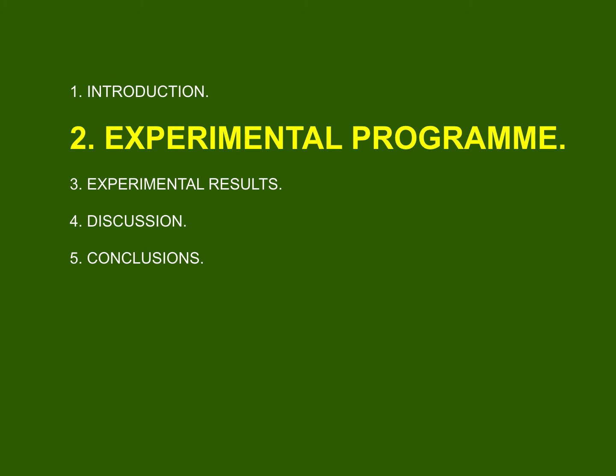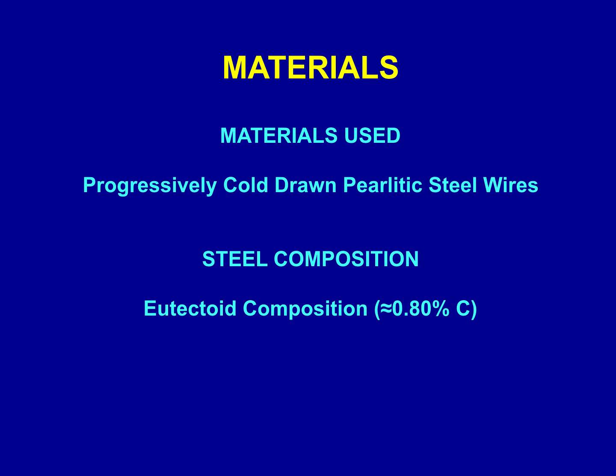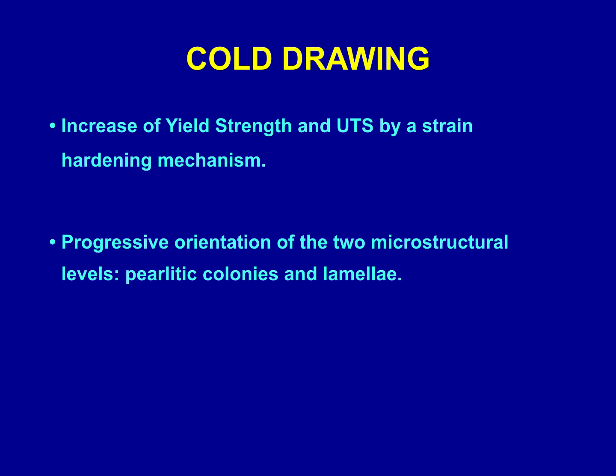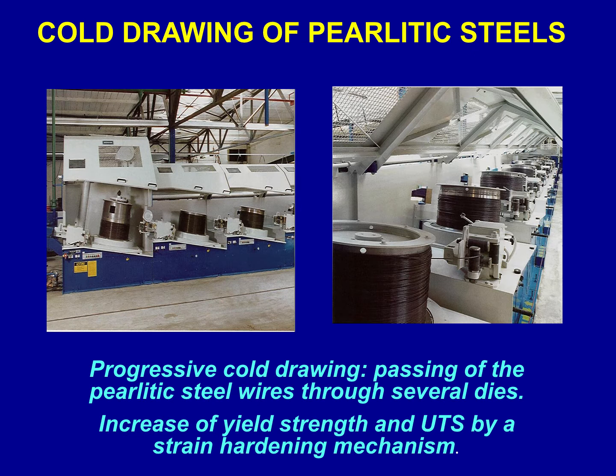Environmental assisted cracking. The experimental program: materials were progressively cold drawn pearlitic steel wires with an eutectoid composition, 0.80% of carbon, and cold drawing produces an increase of yield strength and UTS by a strain hardening mechanism, with progressive orientation of the two levels of pearlitic colonies and ferrite cementite pearlitic lamellas.